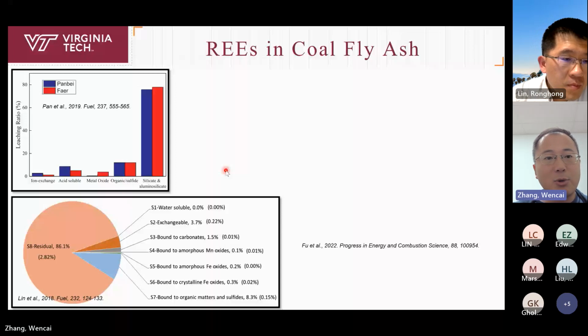So in many studies, it has been found that rare earth in coal fly ash has a low leachability. And a lot of researchers did sequential chemical extraction. And they found that the reason why the rare earths are very difficult to leach from coal fly ash is because the majority of rare earths are in the silicates and aluminum silicates of the fly ash. As you know, during the coal combustion process, the silicates and aluminum silicates become glassy. They don't have a very good crystal structure, and this is just an amorphous glassy structure.